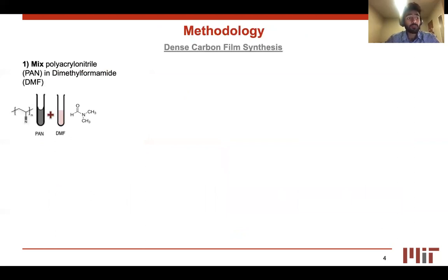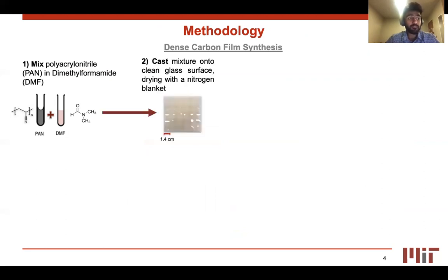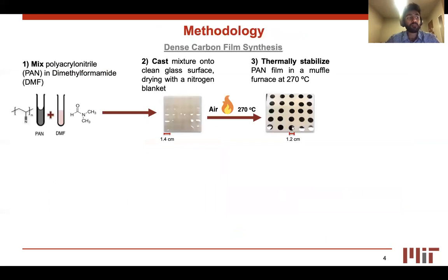First, a bottom-up synthetic process was developed to produce non-porous and planar carbon films. The first step involved mixing polyacrylonitrile and dimethyl formamide into a viscous solution. Next, the viscous solution is casted onto a clean glass surface under an inert environment until it dries into a polymer film. The third step involves thermally stabilizing the polymer disc in a muffle furnace at a temperature of 270 degrees C. The average retention here was 81% with a standard deviation of 7%.